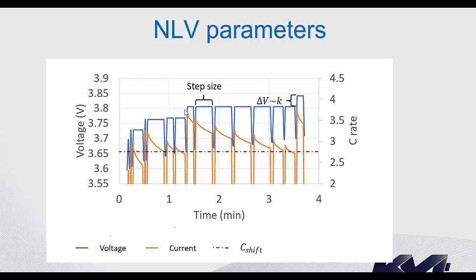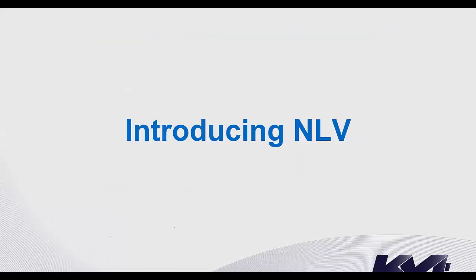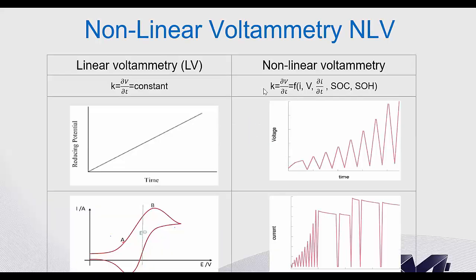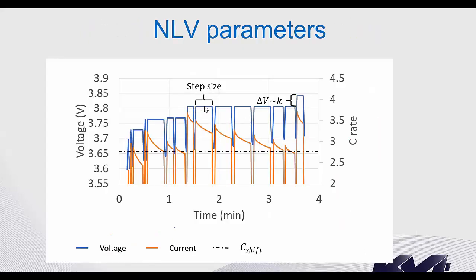So we increase the plateau by a delta V here. And delta V is actually defined by the equation that I showed you before. Okay, here, this equation. So we apply this equation, and that gives us the next plateau. And we repeat this plateau as often as possible until we go to the next plateau and so on.